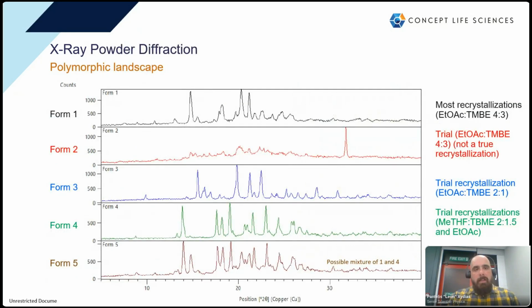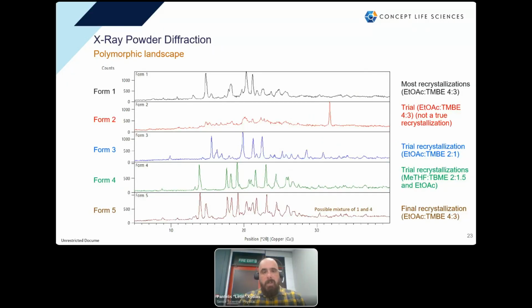So to catch up from where Jen stopped, as she said, we identified 4 different forms, forms 1 to 4. Form 2 was not really a polymorph, which I'm just adding here for completeness. It would be strange not having a Form 2. And in the end, we also found a Form 5, which, as I will show you, wasn't really a form. It was practically a mixture between Forms 1 and 4. After this, we assessed the materials with DSC, and we found really strange results.